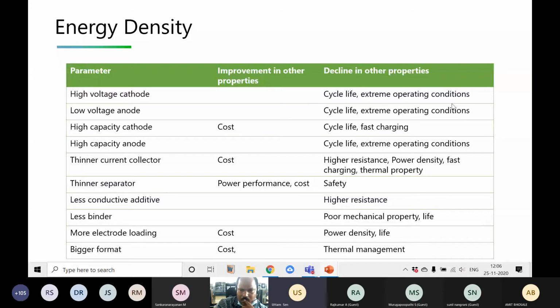We cannot operate at extreme operating conditions. Similarly, with a low voltage anode, cycle life and extreme operating conditions are going to be hampered. If we use a high capacity cathode, we improve in terms of cost, but again cycle life and fast charging are going to be hampered. In case of a high capacity anode, mostly silicon, again cycle life and extreme operating conditions are going to be hampered. So these are the paths by which we can achieve higher energy density, but at the same time we have to compromise on some parameters. Eventually we need to solve all those issues to achieve high energy density.